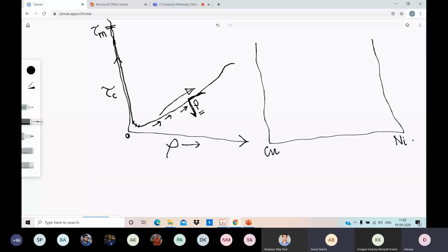To move a dislocation, more stress is required when less dislocation is present. When there is zero dislocation, how much stress do you need to apply? High. Theoretical. It's very, very high because you have to create a dislocation.